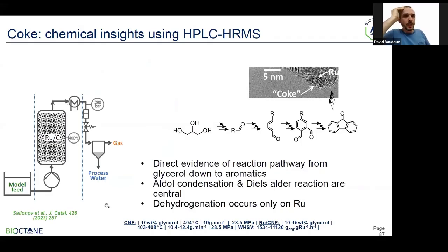Next slide, please. Again, making a very long story short, we were able to identify a mechanism, a reaction pathway, that yields the formation of aromatics that deposit on the catalyst. We identified aldol condensation, which are steps 2 to 3, and a Diels-Alder reaction, steps 4 to 5, as the core steps that yield aromatics and polyaromatics. You have a good example on the right of one compound that was present in high concentration, and it's a starting point for the formation of larger polycyclic aromatics. It's important to stress that dehydrogenation occurs only on ruthenium, and that was not observed on the support itself. Next slide, please.